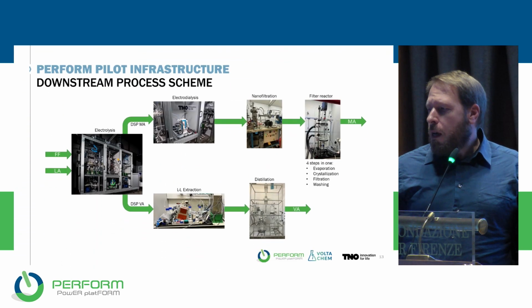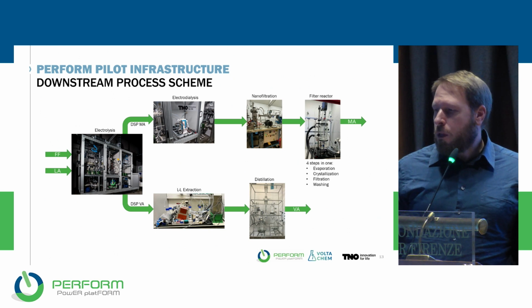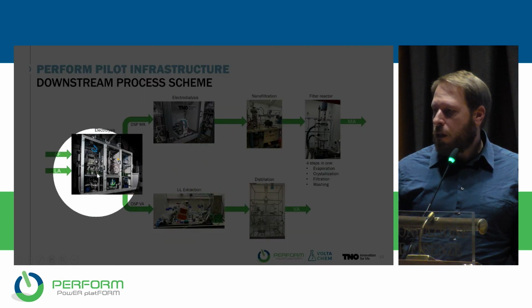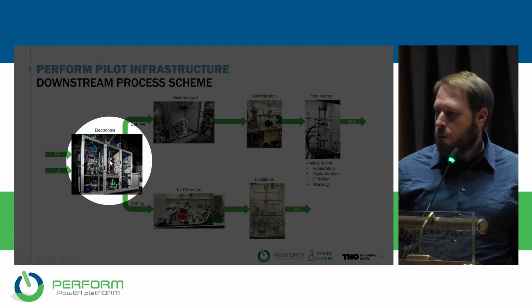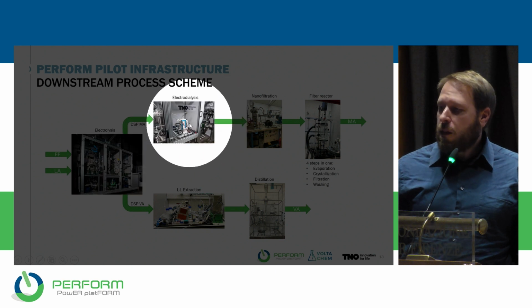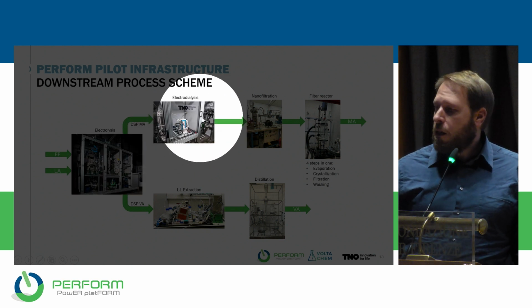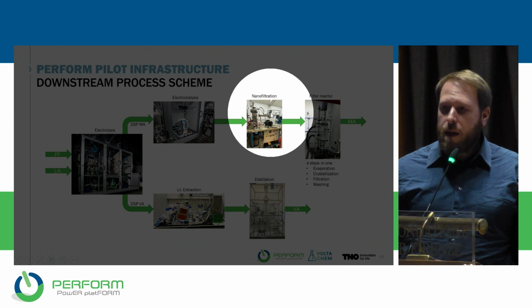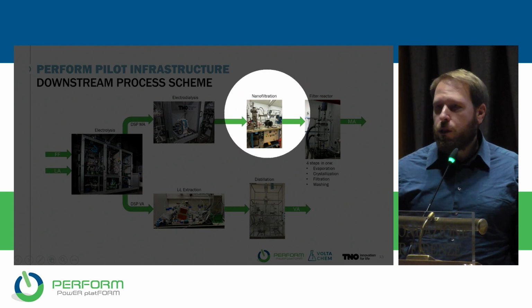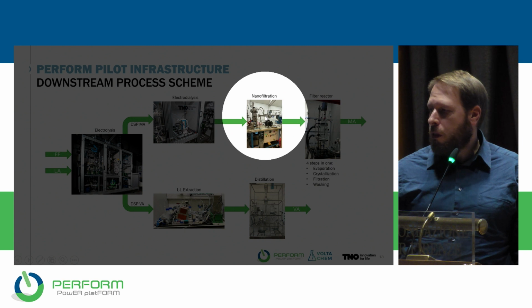As I said, we also looked at downstream processes, and as was mentioned before, from the upstream unit, if we look at the furfural to maleic side, the first step is electrodialysis to remove sulfuric acid. Then we have a nanofiltration step, and this serves as a concentration step to remove most of the water.